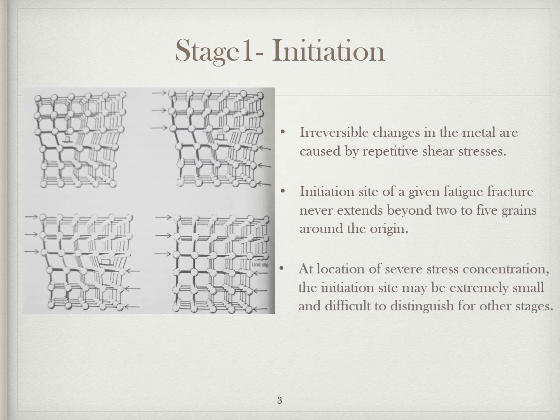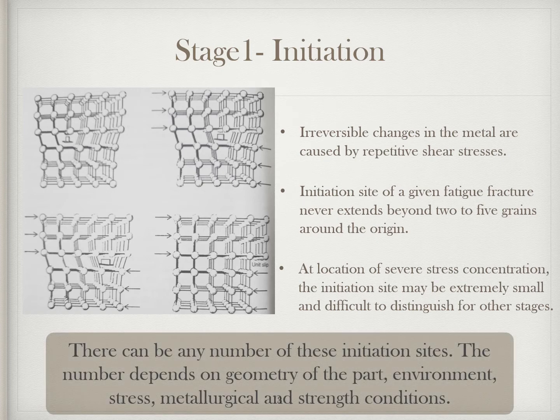The initiation site of a given fatigue fracture never extends beyond 2 to 5 grains around the origin. At the location of severe stress concentration, the initiation site may be extremely small and difficult to differentiate from the succeeding stage of propagation. One must be aware that there can be any number of these initiation sites. The number depends on the geometry of the part, environment, stress, and metallurgical and strength conditions.